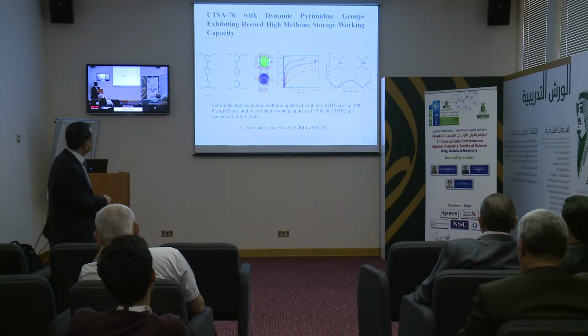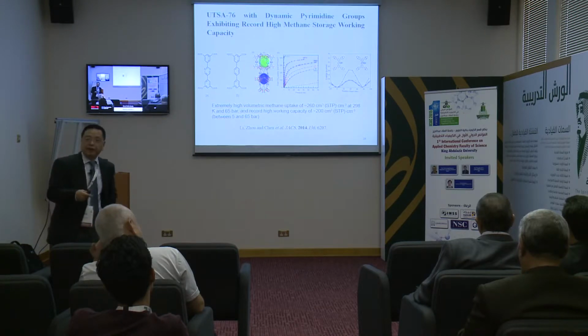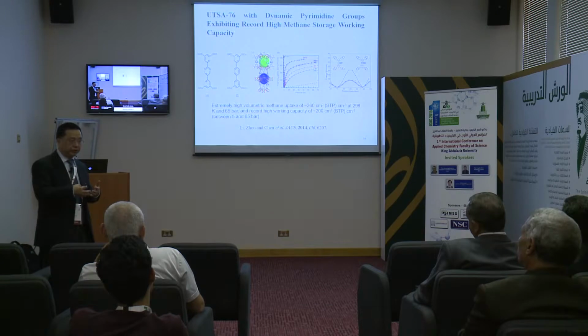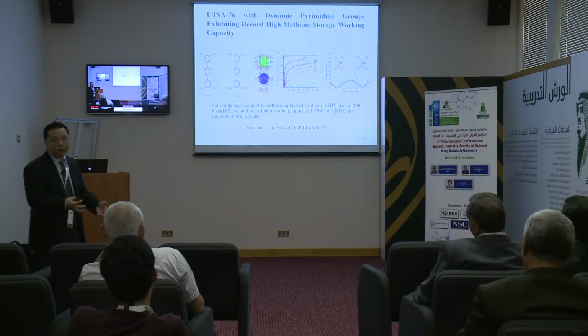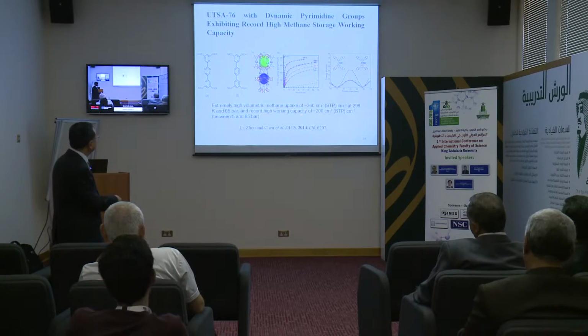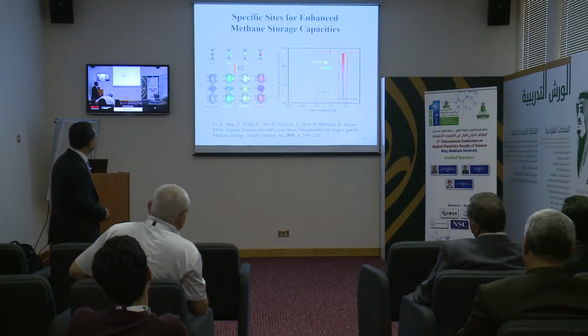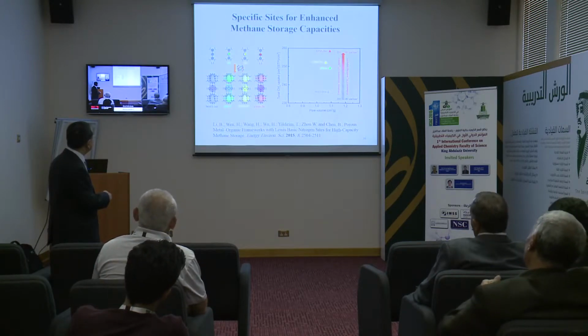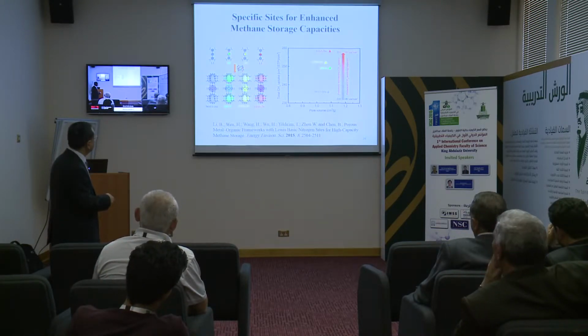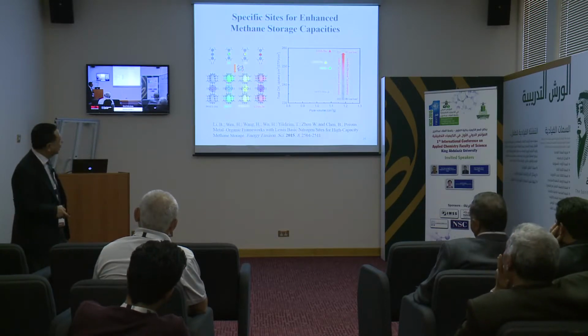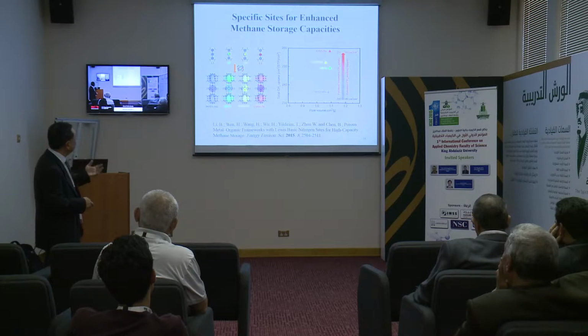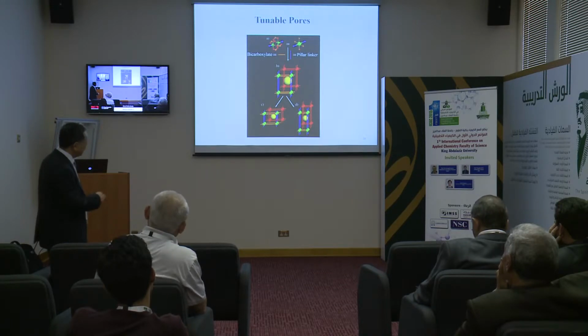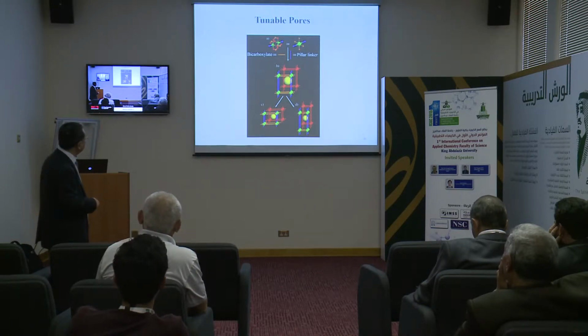And furthermore, this material has a record we call the delivered amount, the working capacity. The working capacity is defined as the storage capacity under storage condition minus the storage capacity at basically 5 bar or 5.8 bar, because it is not convenient and costs energy to remove all the gas down to 0 bar. So the difference we call working capacity, and this is quite high. We used different kinds of sites, systematically, and we show that this uptake can be tuned systematically. So indeed, this functional site can help to enhance the storage capacity to a certain extent, but it is still very, very challenging.